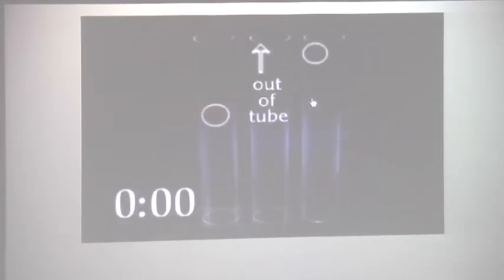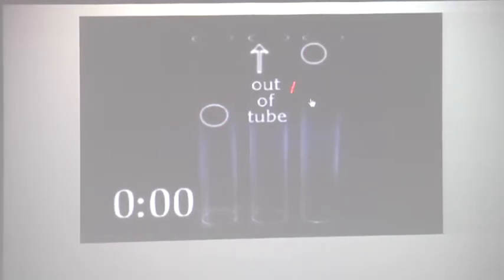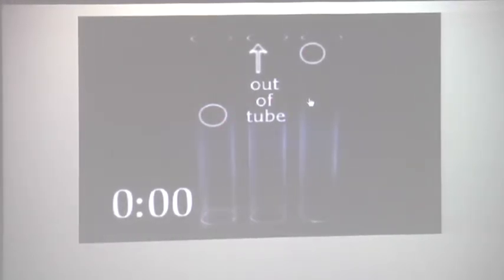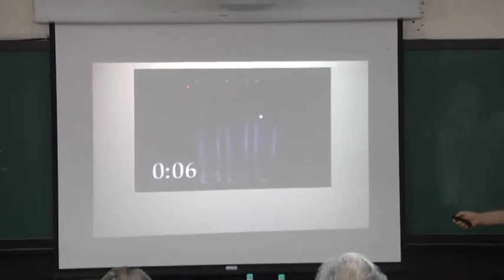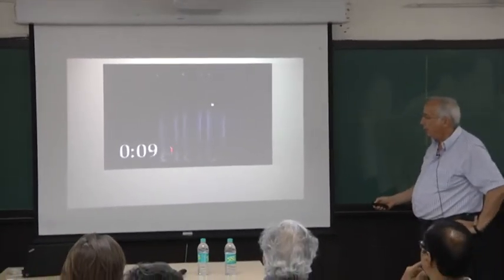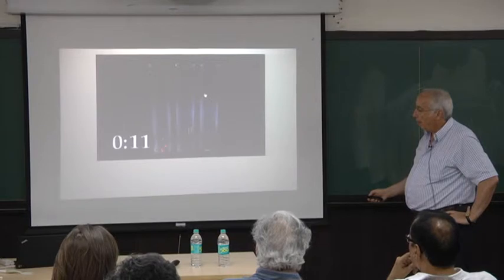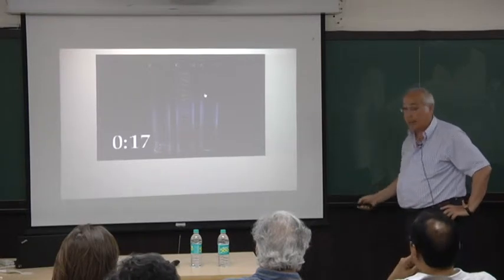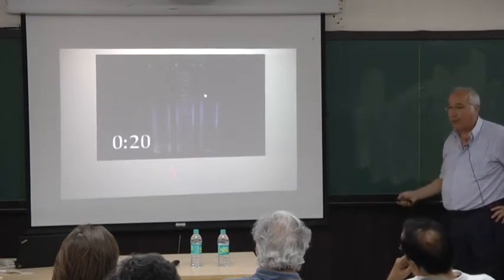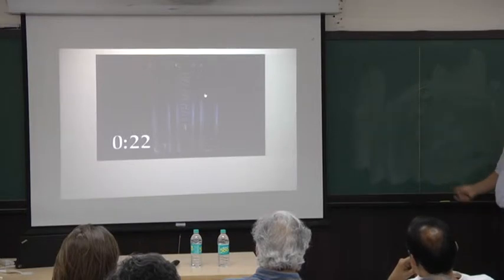We threw a ball from upstairs. Here it jumped up to here on the steel, here up to here, and here it went out of the tube. The restitution coefficient of the metallic glass is much larger than either steel or titanium. Now we threw them from the same height. You see on the steel, it is jumping, and in a short while, it's going to stop. Here on titanium, it's almost going to stop. On the metallic glass, the same ball continues to go up and down, up and down, up and down.